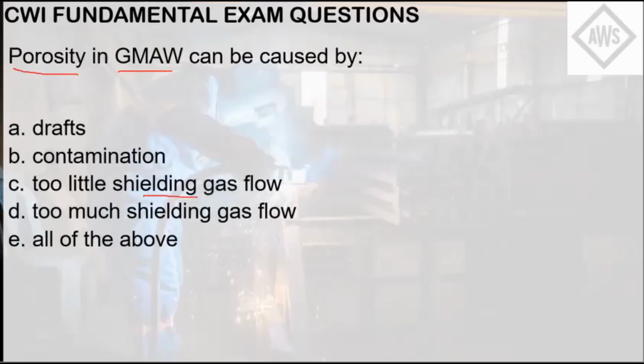Also, too much shielding gas flow can cause porosity. So why is that? If you have too much of a flow in there, it can create a vortex that induces vacuum conditions around that weld puddle, and that will cause it to suck the gases into that weld puddle and will cause porosity later on. So too much is also not good. It should be the right amount as specified in the welding procedure specifications. So the answer here is letter E, all of the above.